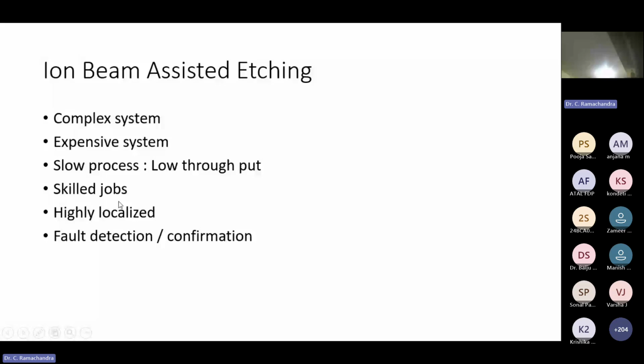Sometimes you don't want to remove the material throughout the silicon chip. You want to remove it at one selected point. You want to remove maybe 1 micron, 0.5 micron. Therefore, that kind of application, failure analysis, fault detection, fault confirmation, it is used. It is not used for manufacturing. Once again, remember, it is highly localized. Plasma etching is global. That means it etches the whole wafer. It does not discriminate any location. It is very fast. We can put 25 wafers, wafer by wafer. Very fast actually. Ion beam etching is very low throughput because here we are etching at one particular location, maybe 1 micron, 2 micron. Therefore, it is useful only for troubleshooting purposes, not for manufacturing.